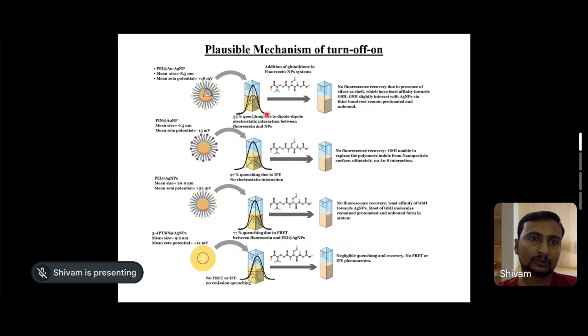So, what was the plausible mechanism for turn off and turn on detection? PI stabilized bimetallic nanoparticle quenched the fluorescein via dipole-dipole interaction with 53%. However, after the addition of glutathione in the fluorescein and metal nanoparticle system, no fluorescence recovery happened due to the presence of silver on the shell.